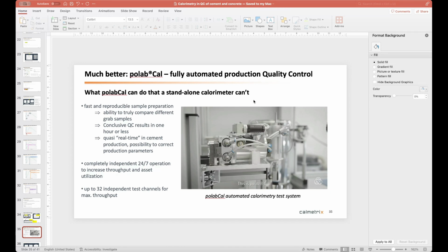The rule of thumb is if you test anything that has admixtures in it, you do want a mortar test. And quite frankly, it's not realistic to think that any concrete or cement today is used without admixtures. So it's a good idea to very often test with mortar. The reason is that many admixtures, the majority of the newer generation admixtures, are sensitive to the mixing energy. And the mixing energy you get just with paste is completely different from what you get in the real world when you do concrete or mortar. Mortar and concrete is similar. That mixing energy has pockets of heat that are localized and that make the additives react very differently.